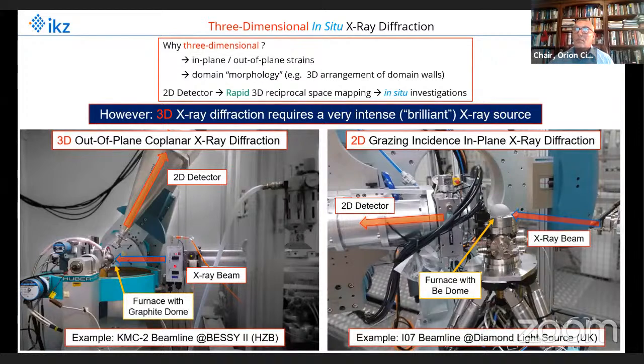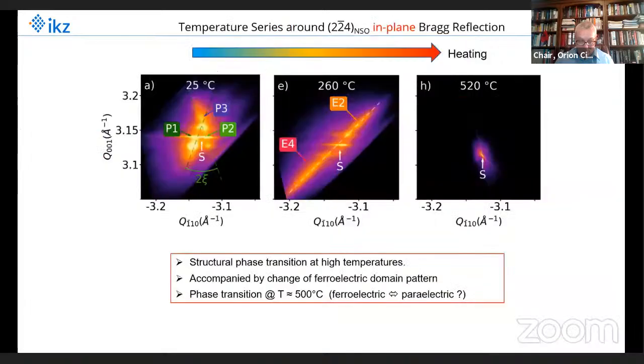And you can distinguish, you can now do really true 3D out-of-plane coplanar X-ray diffraction, but you can also concentrate on grazing incidence in-plane X-ray diffraction, where we have only investigated this in 2 dimensions. And the first example is when you measure the diffraction pattern at different temperatures.